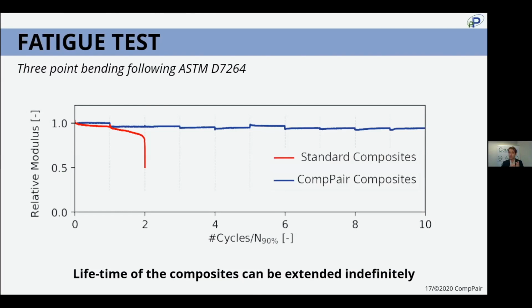And what you see here is a typical modulus on the left for different healing cycles. And what we have done was to take the sample and get some fatigue testing, and then see how they can recover damage after they are damaged at a 90% probability of failure. We stopped the test, we healed the samples, we redid the test again, and what you can see is the fact that for standard composites in red, this is a failure after 2 cycles. And for CompPair composites, basically, you can highly extend the lifetime of the composites for a lot of time as compared to standard composites.